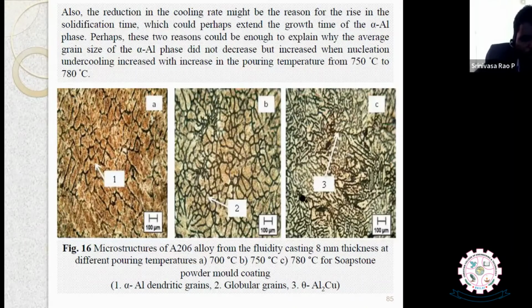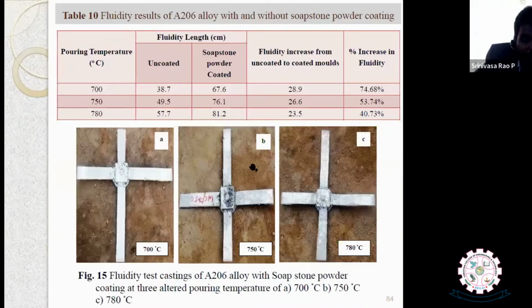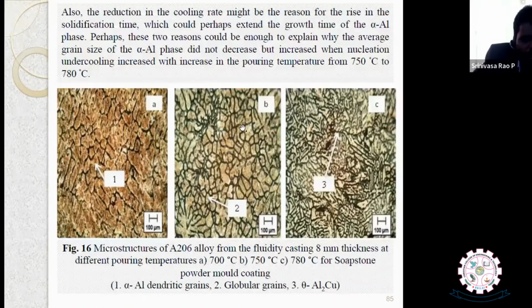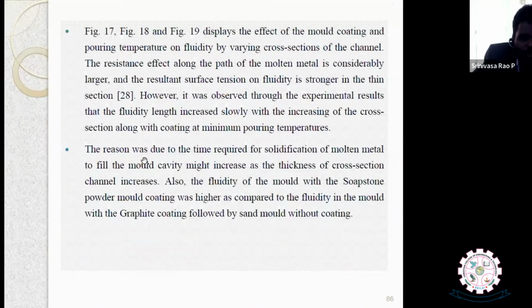is with soapstone powder only. Because of the high melting point and high resistance, the fluidity increase is more as compared to the uncoated and graphite. So soapstone powder has given the best results as compared to the previous coatings. Okay. See in this one, at 750 degrees centigrade, we see more globular grains, you can say more equiaxed grains. If the equiaxed grains are more, then the material will be stronger.